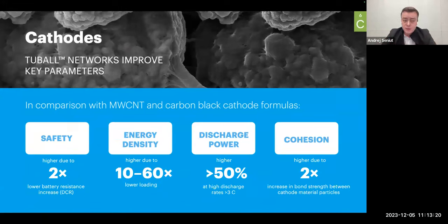So higher battery safety due to lower battery internal resistance, high energy density because the loading of single carbon nanotubes is from 10 to 60 times lower in comparison with carbon black and multi-walled carbon nanotubes. This is why you can put more active material inside the battery to achieve high energy density. Third one, this is higher discharge power. Typically, this is observed at very high discharge rates, higher than 3C, 4C, 5C, where already conductive network plays the role in such kind of performance.